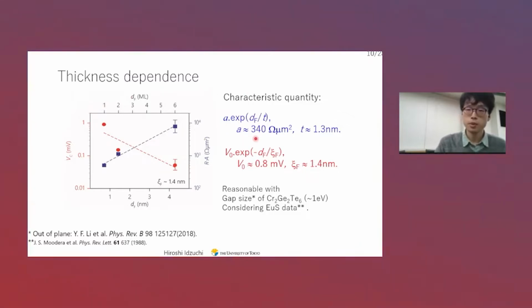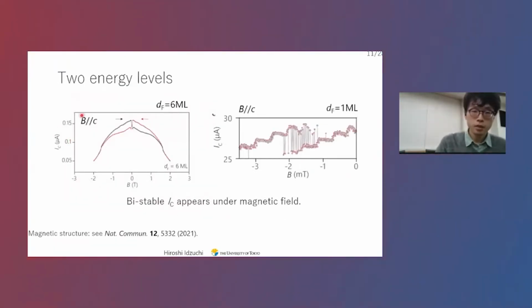So we have some resistance coefficient of tunneling behavior, and also thickness characteristics, which is about 1 nanometer. I skip the details, but with gap size and so on, it's reasonable. And then if we look at the critical current with various magnetic fields, in fact we have some hysteresis. That's somewhat unusual. If you decrease the magnetic field, the critical current is higher, but at some point it jumps, and there is a hysteresis.